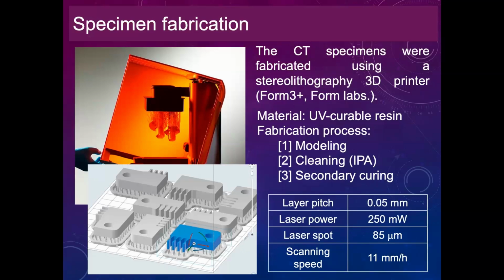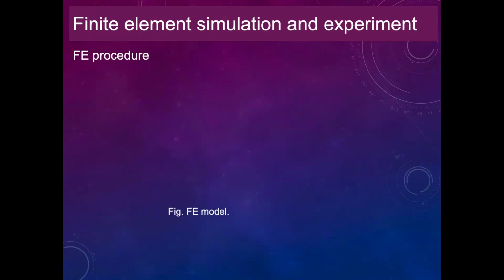In this case, the layer pitch was set to 0.05 millimeter, the laser power was 250 milliwatt, the laser spot was 85 micrometer, and the scanning speed was set to 11 millimeter per hour. And here we want to explain the finite element procedure.